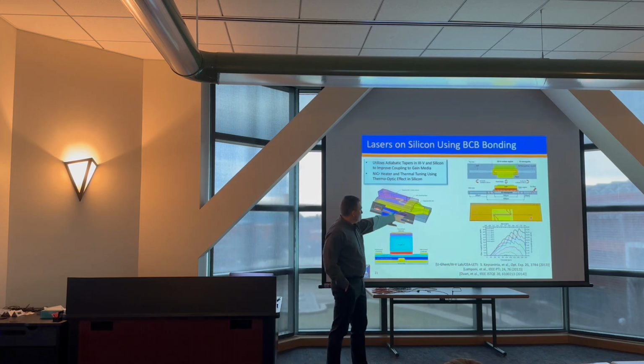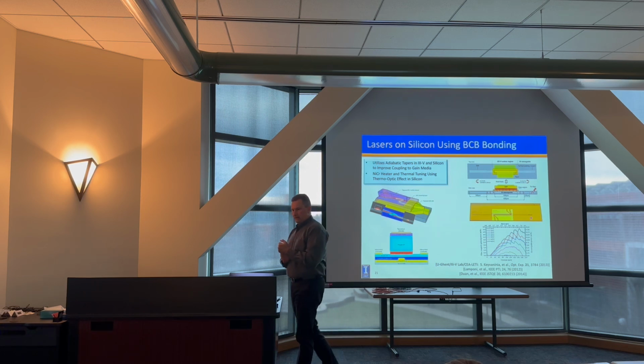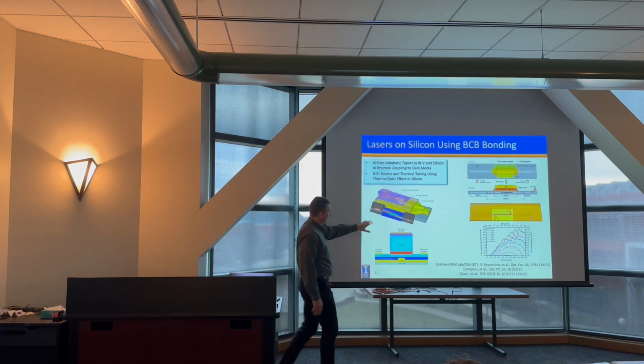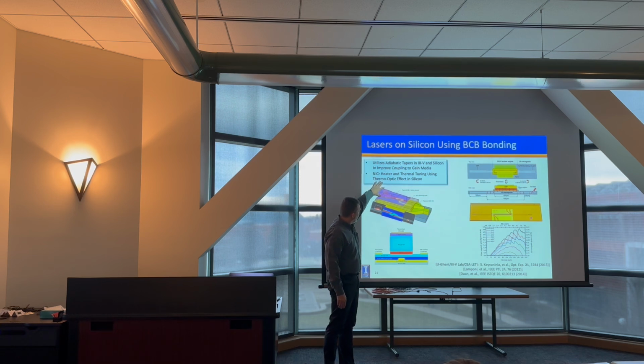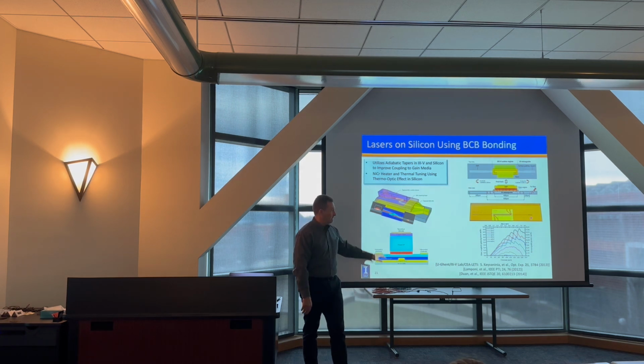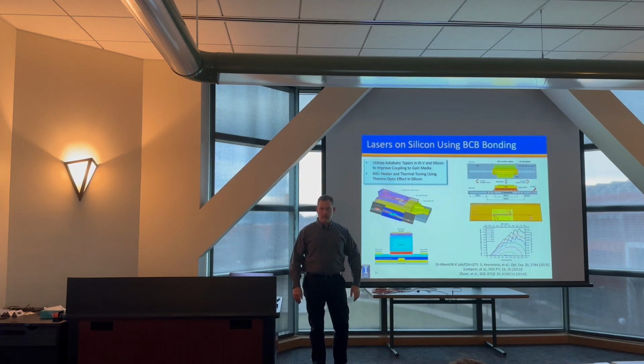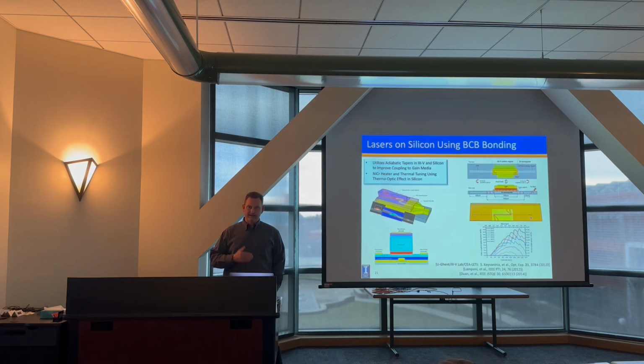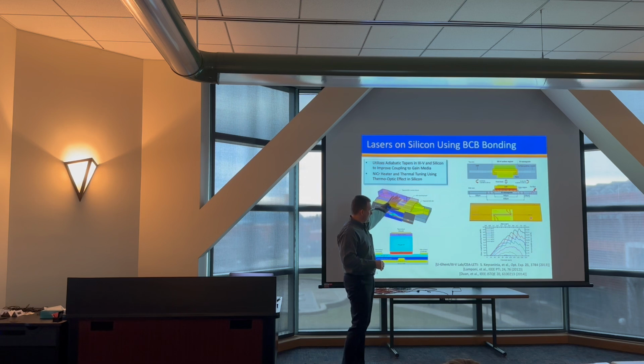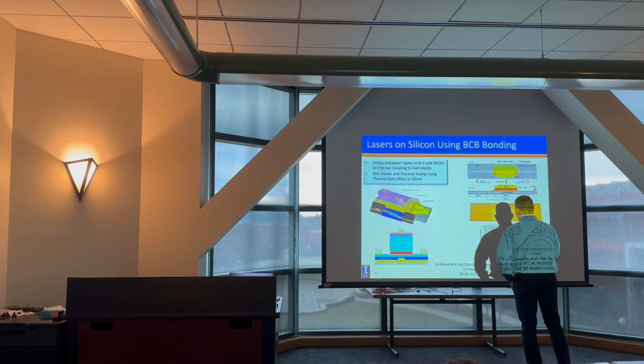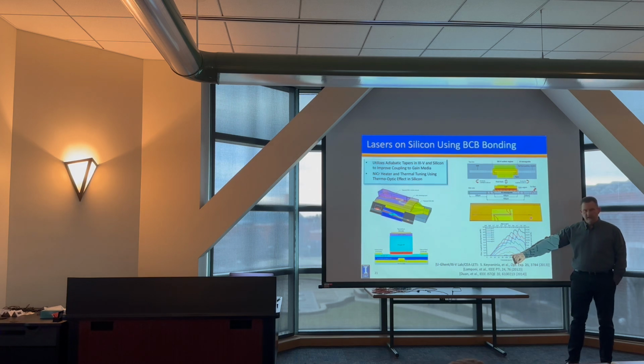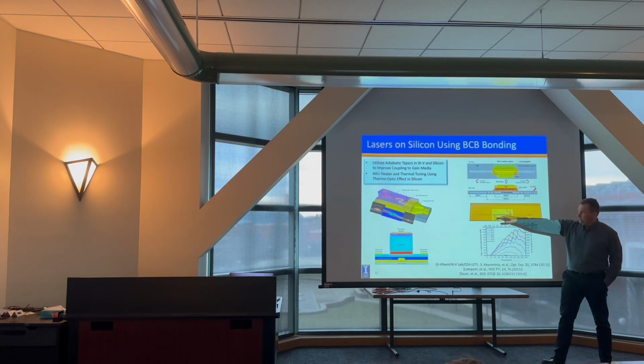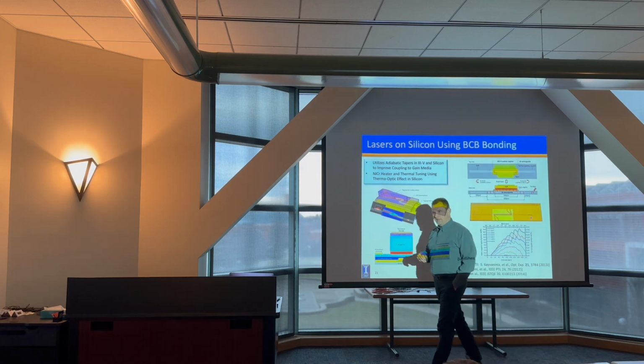The folks at Ghent made 3-5 lasers on silicon using BCB bonding. So they basically took a 3-5 layer, patterned that and etched it such that there was a taper. In the gain region, you'd have propagation of your 3-5 material. At the edges of that, they would couple into a silicon waveguide, and they were able to make lasers on silicon using this approach, but again, the lasers were not great, higher thresholds and not really good thermal performance. And part of that was because of the thermal environment created by that BCB. Okay.